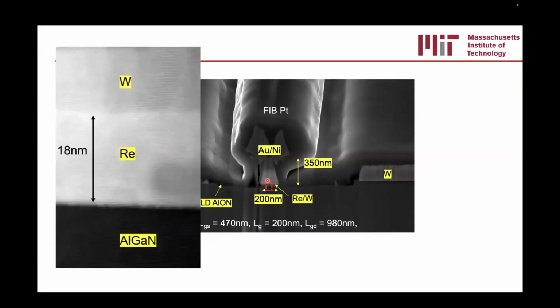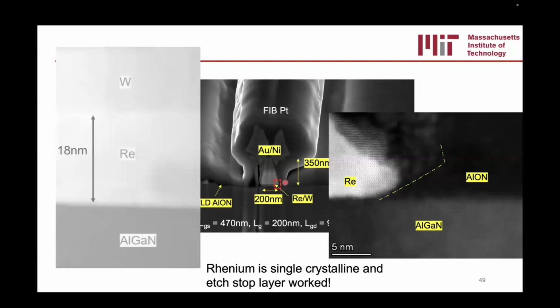Additionally, if you look a little bit on the edge here of the gate, you can actually see that the etch stop layer actually worked, where we're able to see that the rhenium has this little curvature here, and the aluminum oxynitride also has a curvature here from the fact that the developer was an isotropic etch. We're able to remove that very nicely.